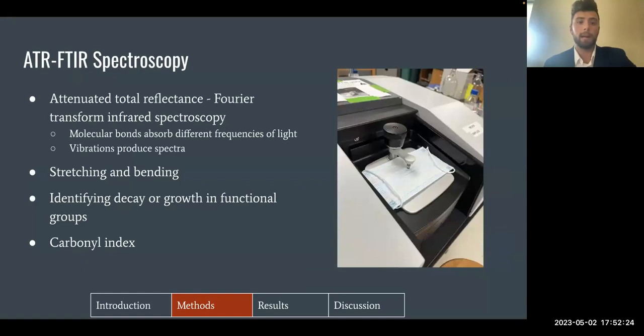After the masks were dried and weighed, light transmission measurements were taken and the water was filtered. The masks were taken to NSU's main campus in Davie, Florida for attenuated total reflectance Fourier transform infrared spectroscopy readings. Different molecular bonds absorb different frequencies of light, and their reactions, i.e. vibrating, stretching, and bending, provide an identity for each bond and quantify the degree of degradation over time. Degradation metrics are generally displayed as indexes, and the ATR FTIR can measure the indexes of different functional groups in either solid or liquid samples.